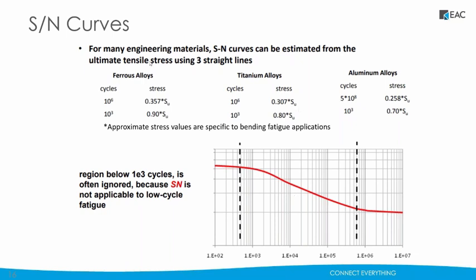What I wanted to point out was that because of this straightness of the flat line here at the endurance limit, it turns out there's a pretty consistent relationship between the stress level of that endurance limit and the ultimate tensile strength of the material. So I've seen a lot where people will compare it to yield stress and just say, well, we don't do fatigue evaluation, but we just compare it to yield, and we call that good enough for our products. That's always worked.